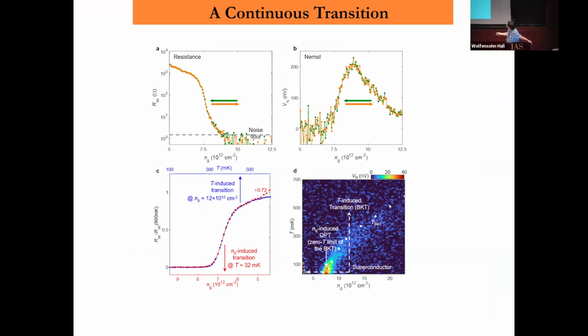It's also, if you look at resistance as a function of gate, this transition, the blue is temperature driven, red is density driven. So it goes through the transition by temperature and by the gate. They're really similar. So it's a continuous transition that connects two ordered states.